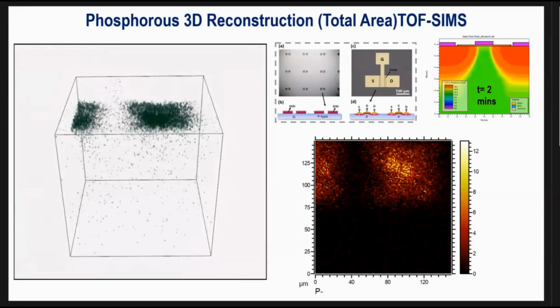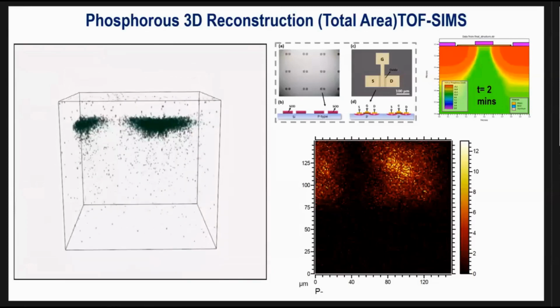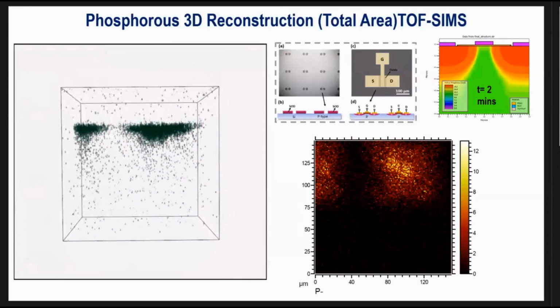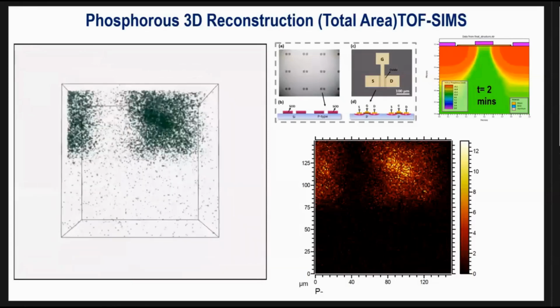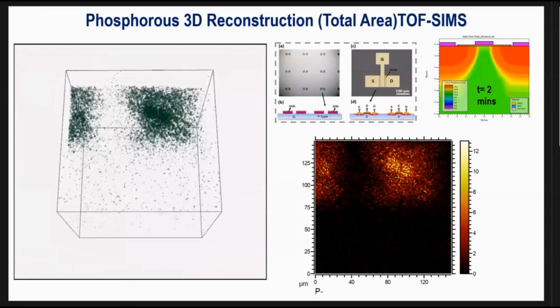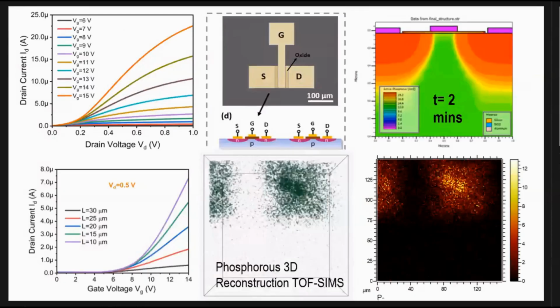So this is a time-of-flight SIMS, and it shows the penetration of the phosphorus into the silicon, and shows the profile. And this took a lot because we don't have a time-of-flight SIMS, so we have to send it out. So we use a lot of modeling, a lot of optimization to do that. And again, it took about 1,000 degrees and about a couple of minutes to do that, but it had to be controlled precisely.